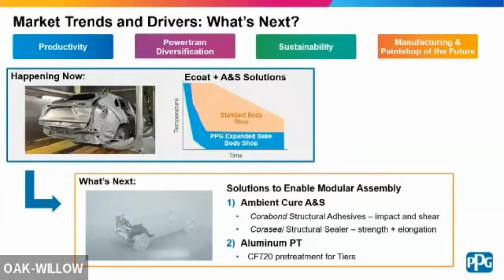And what happens is it generates a lot of sludge. So that's why a lot of our aluminum products, our pre-treats, our new technology that's more centered on aluminum, will go to tiers first, and then we'll move it over to OEM. And that's very deliberate because it's a lot harder in tiers because they do a lot of mixed metal lines. But when you have a straight aluminum line, it's a lot easier to manage because you don't have this continuous sludge generation that has to be dealt with. So it's a little easier on the OEM side to go to lower temperature than it is on tiers.